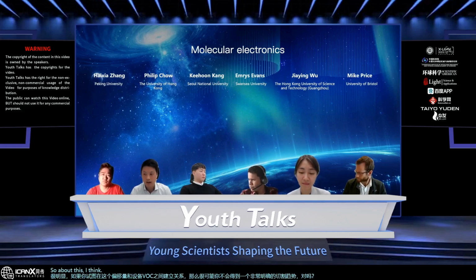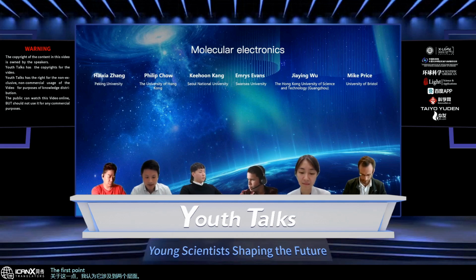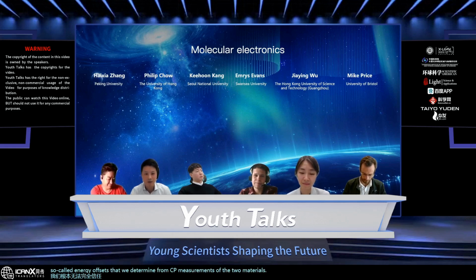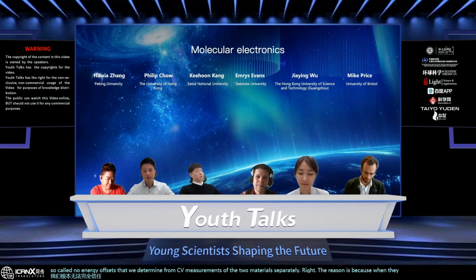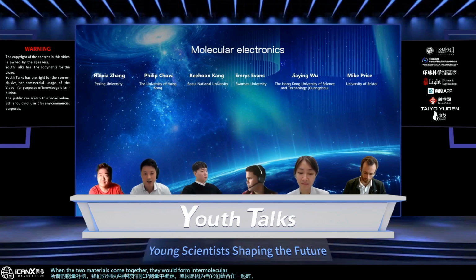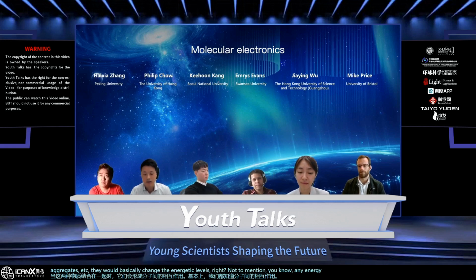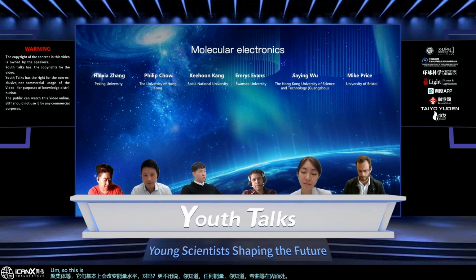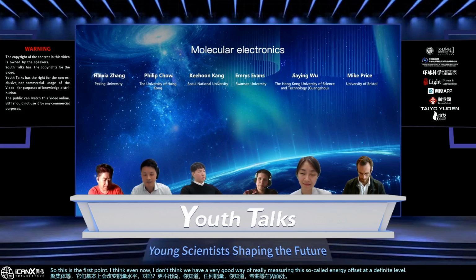So about this, I think it comes to two levels. The first point is that we simply cannot fully trust the so-called energy offset that we determine from CV measurements of the two materials separately. When the two materials come together, they form intermolecular interactions, and we all know that intermolecular interactions, aggregates, etc., change the energetic levels, not to mention any energy bending at the interfaces. So this is the first point. I don't think we have a very good way of really measuring this so-called energy offset at the donor-acceptor interface.